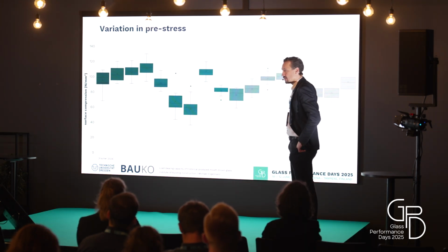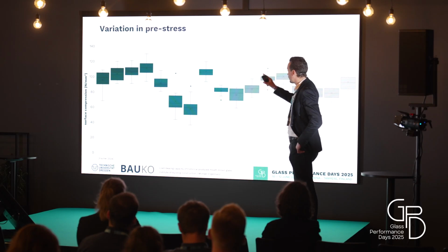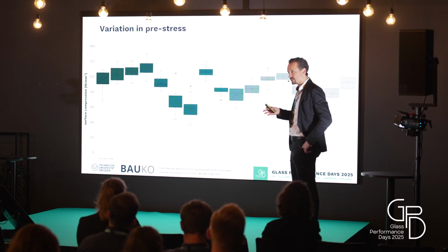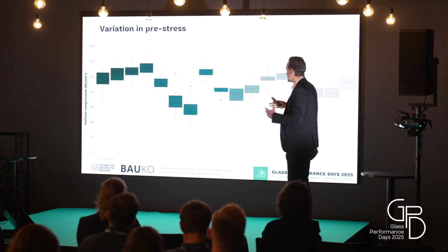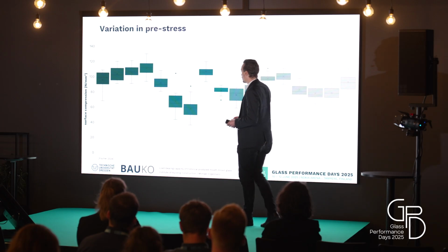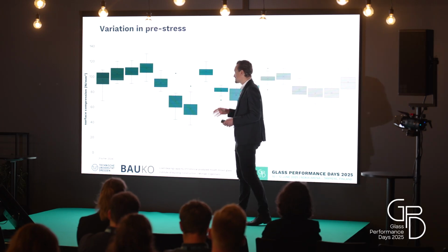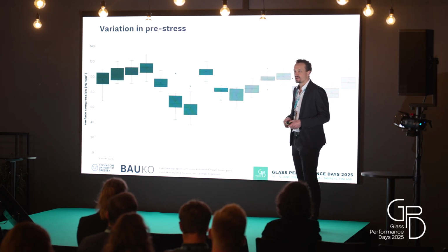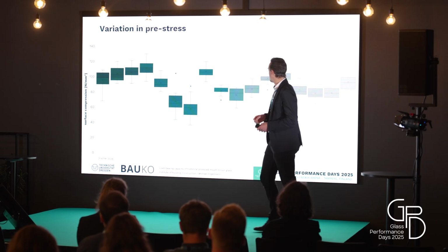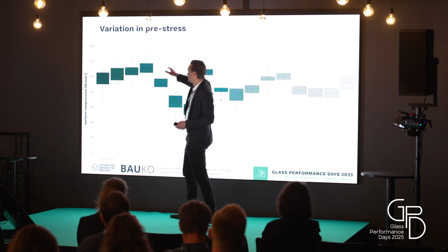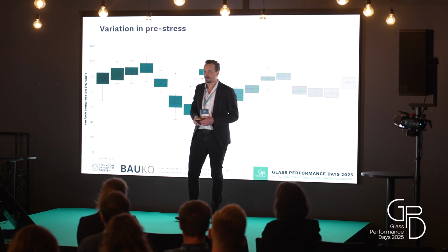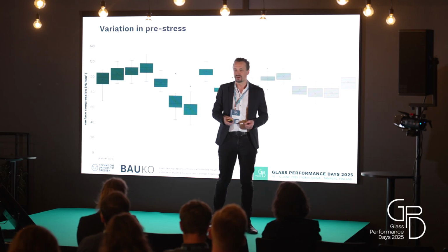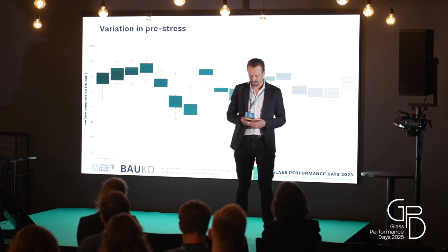And of course, we measured this pre-stress also for 15 samples, so those are all the results here, and we plotted the mean values as well as the spread within single samples, and you see there is quite a variation. The smallest mean pre-stress was around 60 megapascal in compression on the surface, while the largest one was somewhere in the area of 110 megapascals, so we will also find quite a large variation.